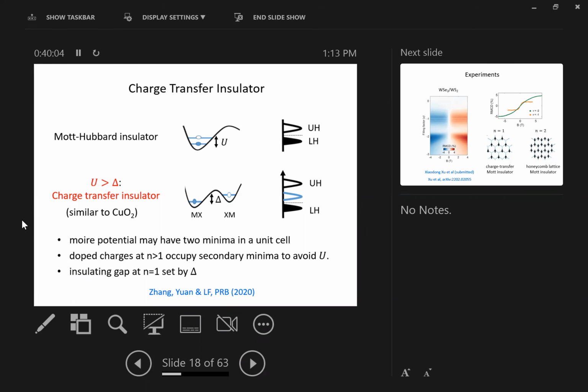So far everything seems to be described by a very simple Hubbard model on the triangle lattice. The idea is that there's a potential minimum on the unit cell, and when you have one electron at every site, you get an insulating state. If you want to add yet another charge, you have to create a doubly occupied site, and that will cost energy U. And this is the standard picture for the so-called Mott-Hubbard insulator. The insulating gap would be set by the Hubbard U.